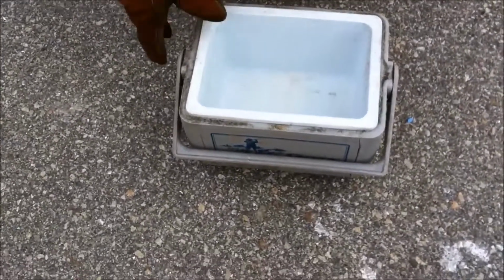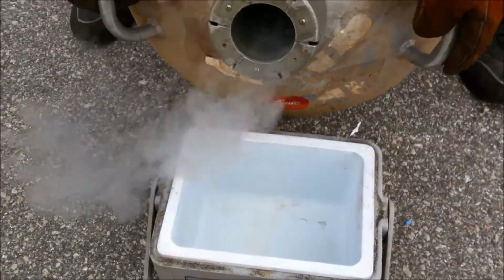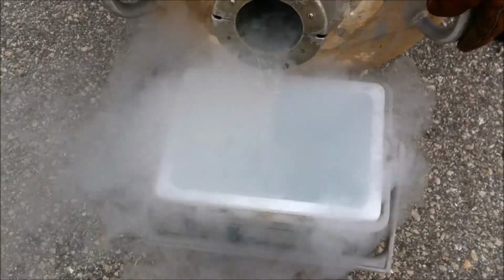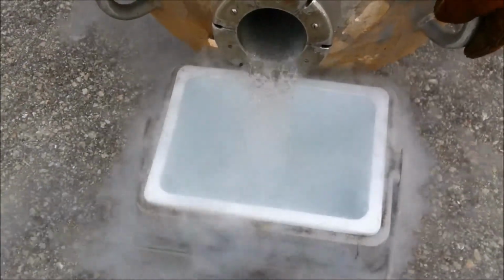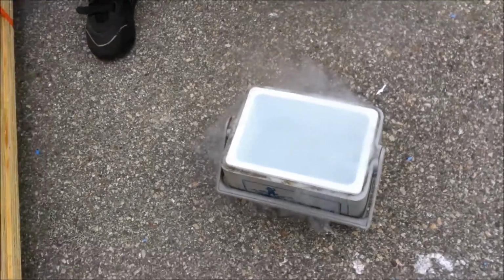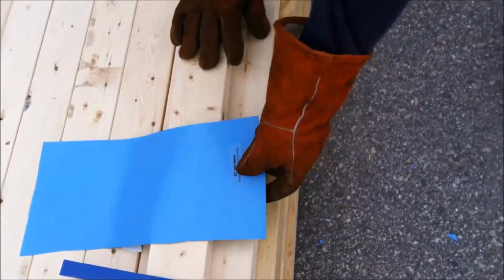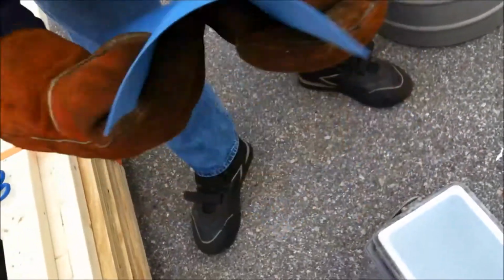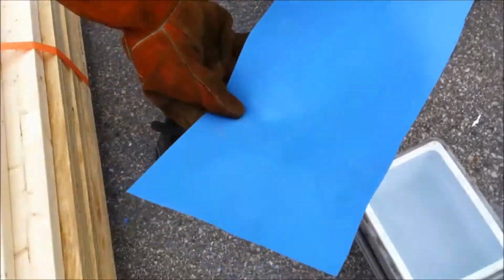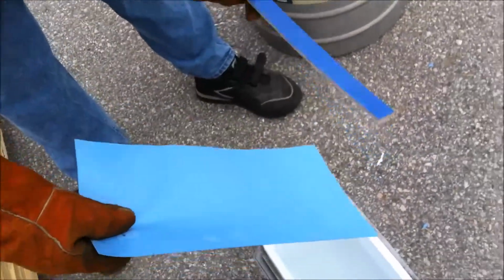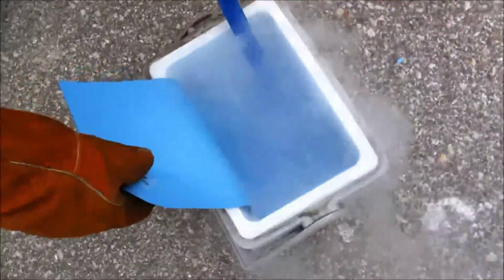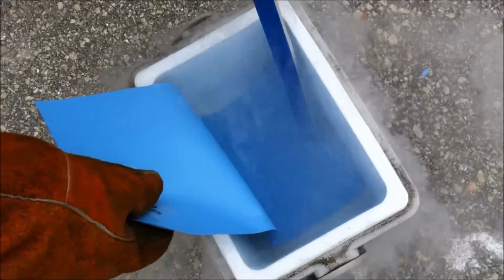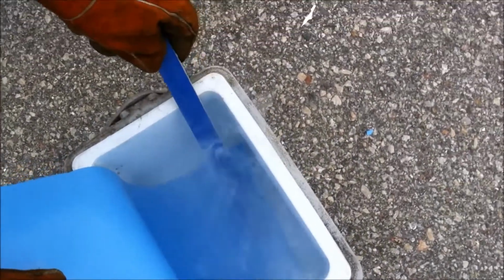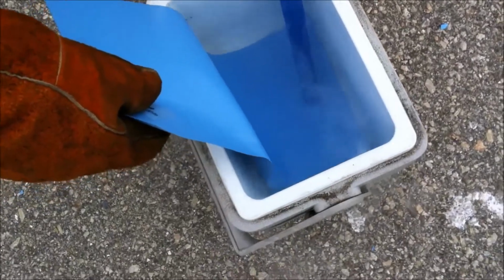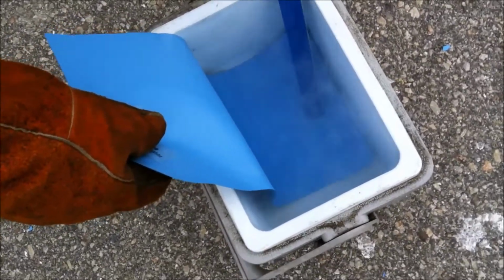So as we pour the liquid nitrogen into the cooler, all right, so that's now minus 320 inside there. And show me the vinyl liner, how it bends when it's at room temperature. And today it's about 60 degrees. So you can see nice and pliable. And then the San Juan stir stick, make sure it gets in there. So here we have 27 mil vinyl liner, minus 320 degrees. We also have the San Juan fiberglass pool submerged in the same liquid nitrogen at minus 320 degrees.